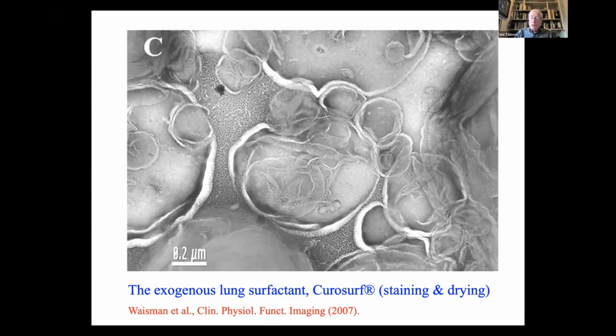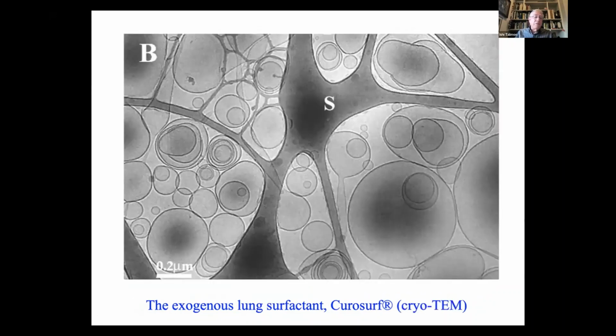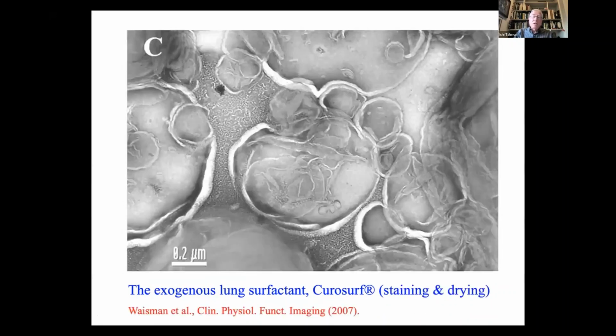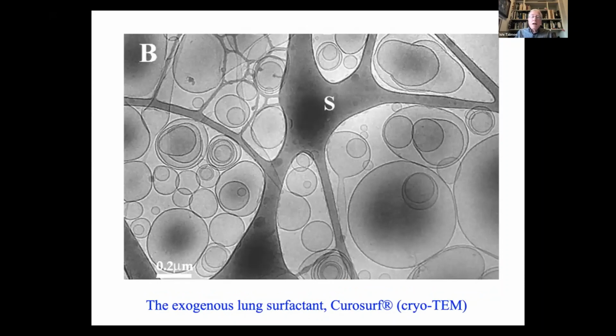Things are very different when you take this specimen, you make it into a very thin film. I'll show you how we do it, and then you cool it very, very fast. If you do that, you see something like this. So instead of this, you get this. What we see here are very nicely preserved liposomes, and as you can see, even in the lung surfactant,